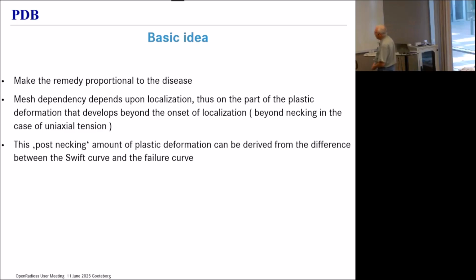Well, the idea is to make the remedy proportional to the disease. I mean, that's what medical doctors do, right? You have a cold, they give you a little bit of penicillin. You have the flu, they give you a little bit more. And we're at the same level here. The mesh dependency will depend on the localization. It will depend on the plastic deformation that we see beyond the onset of localization. So we're going to take our failure criterion, which gives us a plastic strain at failure. And we're going to take the instability criterion, which gives us the onset of localization. And when we subtract one from the other, we have, if you want, the ductile plastic deformation, the part of the plastic deformation that is problematic in the sense that it causes mesh dependency.